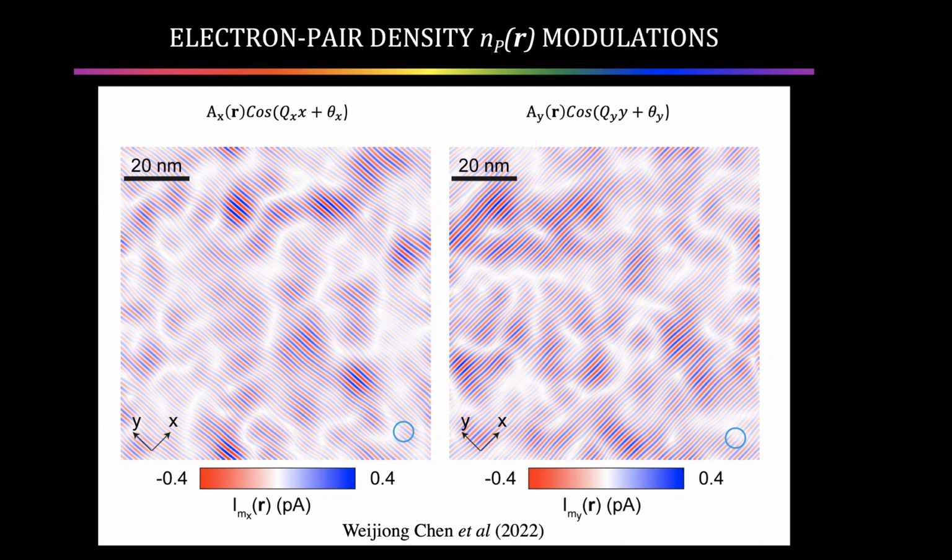Okay. Now with lock-in techniques, we can define the amplitude of the Josephson critical current squared, which is what this is. It's the maximum in the pair current, which is the Josephson critical current squared. We can define the amplitude of that function throughout space and just neglect the detailed modulations at the Q vector.